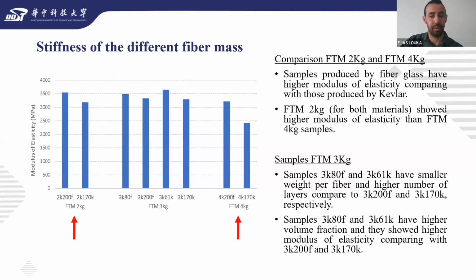For the sample with fiber total mass of 3 kilo, 4 different combinations were investigated, 2 fiberglass and 2 Kevlar. A comparison between the 2 reinforcing materials shows a significant difference in stiffness. Samples 3K80F and 3K 61K have lower weight per fiber and a higher number of layers compared to the other 2 samples. However, because these samples have higher volume fraction, they showed higher modulus of elasticity.